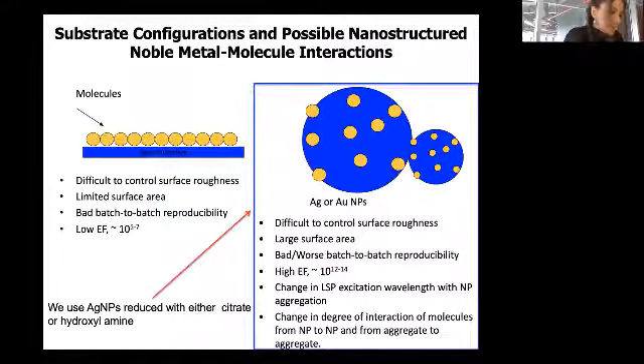But making colloidal nanoparticles is easy. Of course, you still need to be experienced in making this, and there are issues with that. It's not easy to control the reproducibility from batch to batch, but the enhancement can go up to 10 to the 12 to 10 to the 14, which tells us that this technique can be used even for single molecule detection.